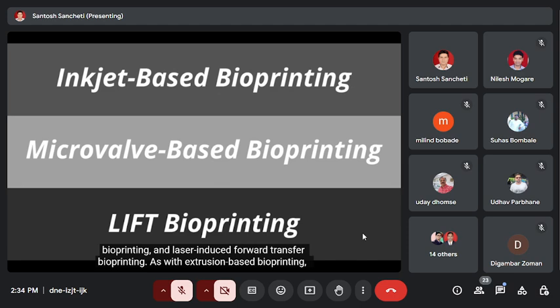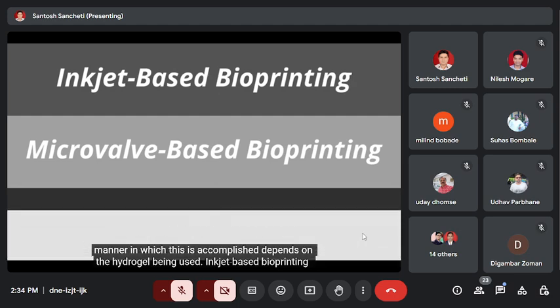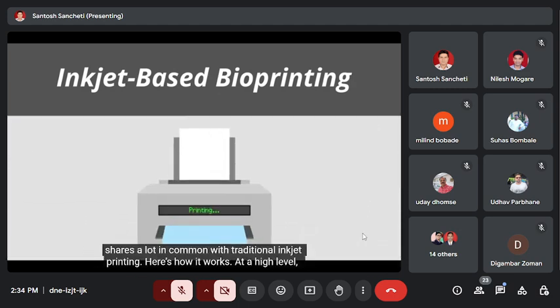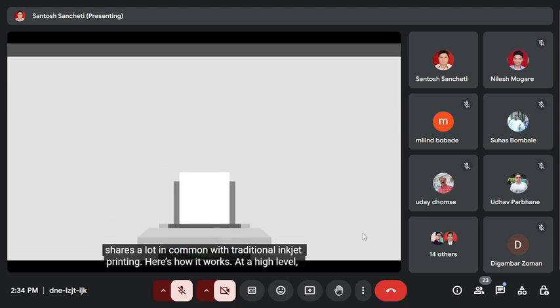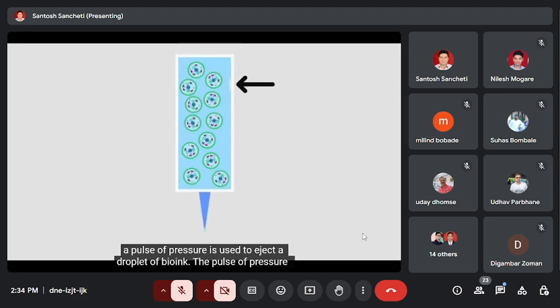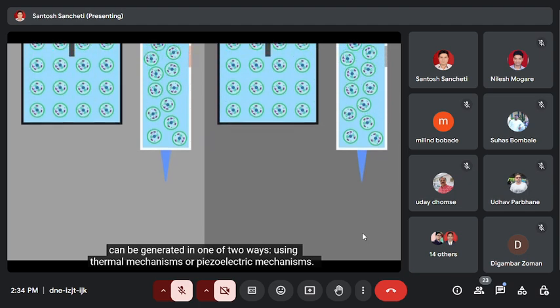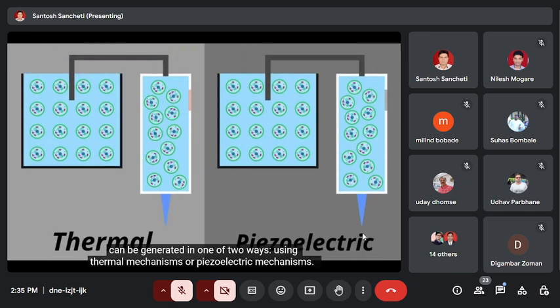As with extrusion-based bioprinting, the bioink must be quickly stabilized in order for the structure to retain its shape, and the exact manner in which this is accomplished depends on the hydrogel being used. Inkjet-based bioprinting shares a lot in common with traditional inkjet printing. Here's how it works. At a high level, a pulse of pressure is used to eject a droplet of bioink. The pulse of pressure can be generated in one of two ways, using thermal mechanisms or piezoelectric mechanisms.